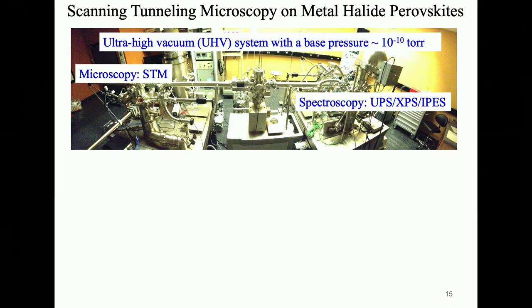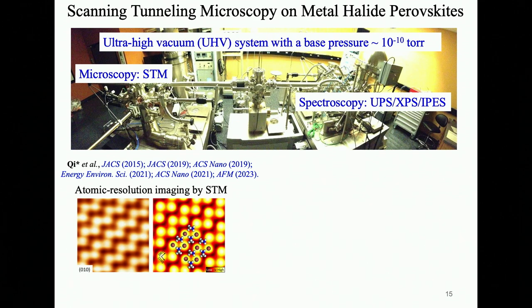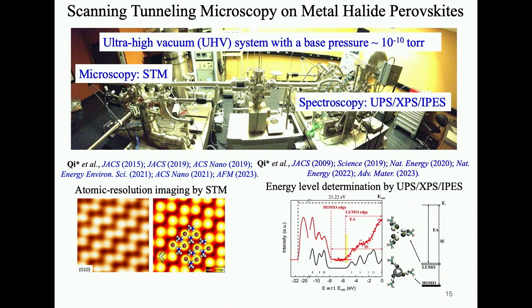So here in this slide, I would like to briefly introduce the major instrument we use for our research works. Here is a photo of the ultra-high vacuum system in our lab. It has a base pressure of 10 to the minus 10 torr, which provides a desirable clean environment for us to perform the atomic scale in situ studies. The scanning tunneling microscopy tool on the left-hand side of the ultra-high vacuum system enables us to determine the atomic structures of the materials. And the spectroscopy tools on the right-hand side of our UHV system can help us understand the material properties better. So here we can establish a one-to-one correspondence between atomic scale structures and their material properties. Also, our UHV system is equipped with multiple vacuum evaporators, which can be used for in situ deposition of thin film samples.